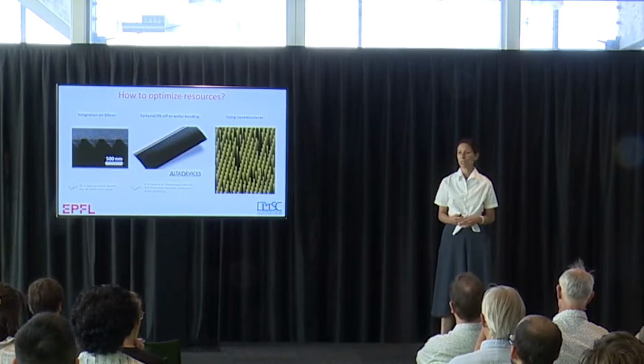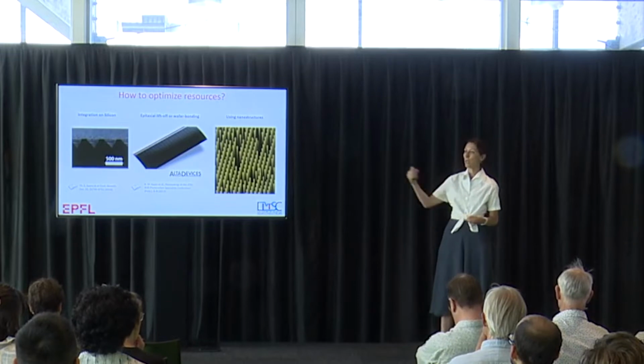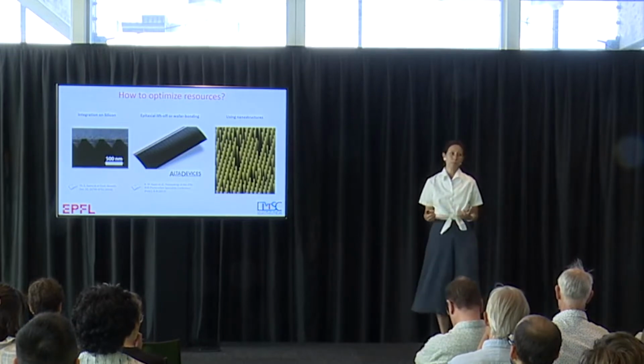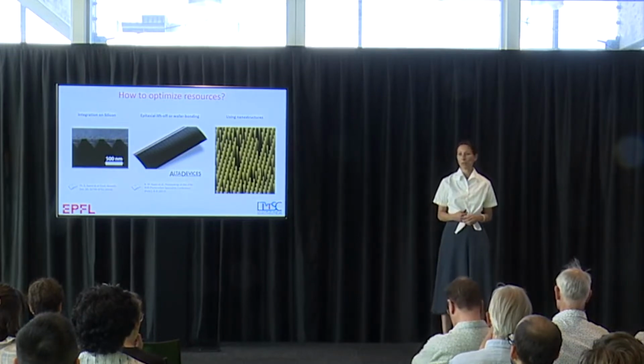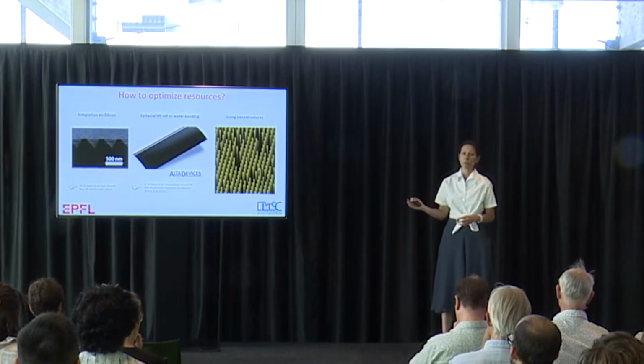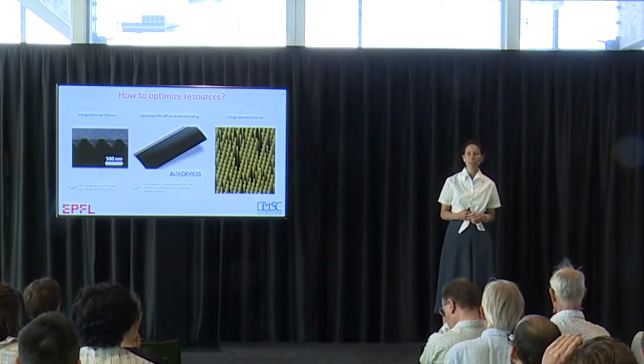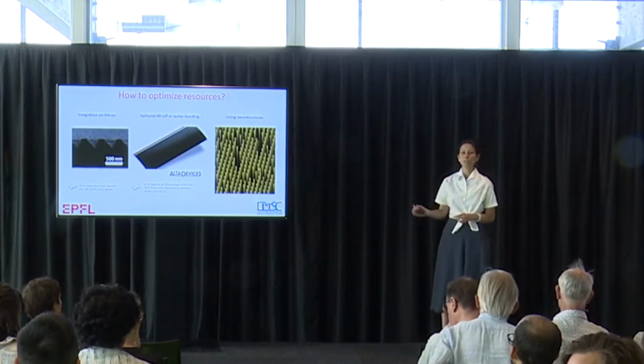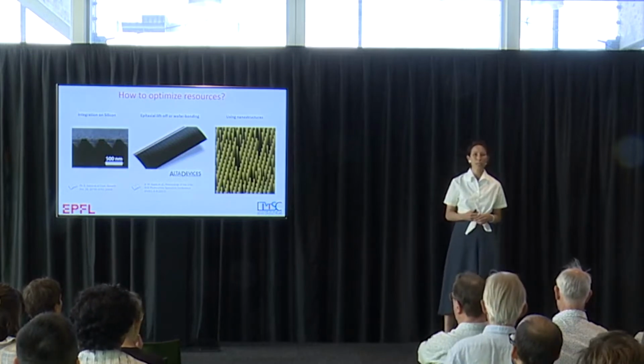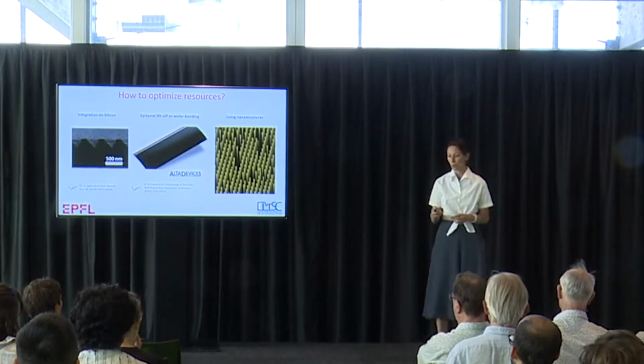You can use a silicon substrate. You can even get rid of the substrate because you can put in a polymer and peel off the device. So in theory, that's a very good path to use very little gallium arsenide. And as I will explain, this also has some advantage for light absorption. Still, we stopped doing this, and there are reasons for that, because I think this is probably not the way to go for real devices.